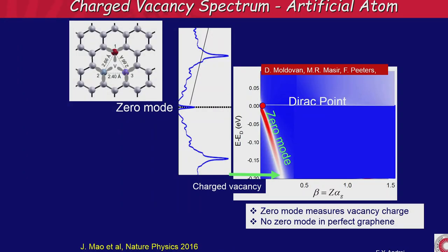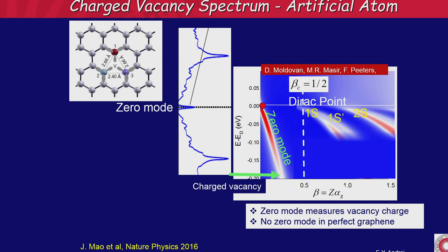Okay, so what's going on? Remember I talked about the zero mode, which has to do with the unpaired electron in the pi band, and it gives you a state here. However, when you charge the vacancy, the zero mode very rapidly moves down, and the amount by which it moves down is a measure of the charge of the vacancy. So that's a very useful tool to have. So here is, and then if you continue charging it, then you should start seeing these quasi-bound states after this thing dropped